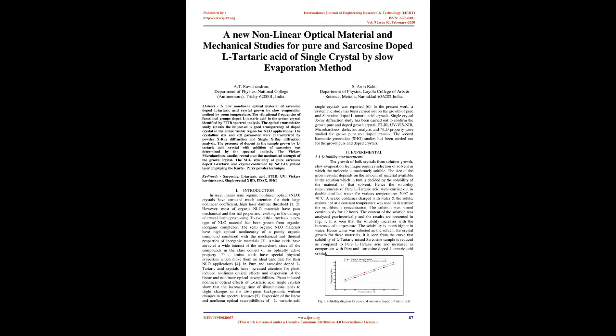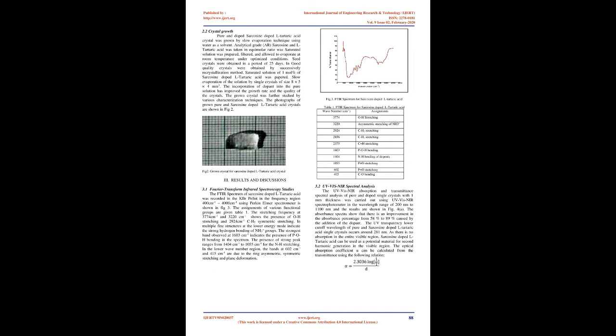A sealed container charged with water and the solute, maintained at a constant temperature, was used to determine the equilibrium concentration. The solution was stirred continuously for 12 hours. The content of the solution was analyzed gravimetrically and the results are presented in Fig. 1. It is seen that the solubility increases with increase of temperature. The solubility is much higher in water. Hence water was selected as the solvent for crystal growth for these materials.